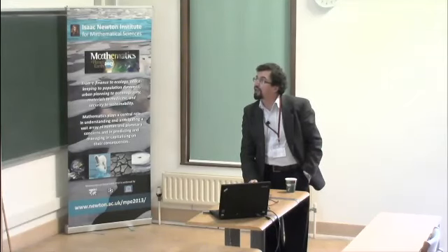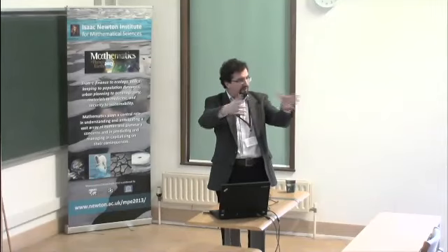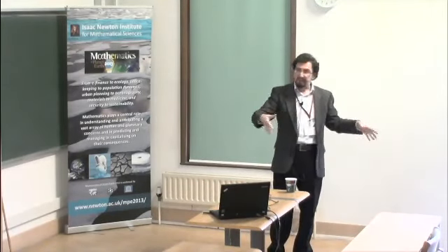By decreasing the temperature in this particular case, you go from a standard texture of a nematic liquid crystal to something that looks, to those who studied liquid crystals, like a smectic. Those ellipses are so-called focal conic domains, and they occur only in systems in which you have some periodicity. And this periodicity wants to preserve itself despite the fact that the liquid crystal is curved in space.